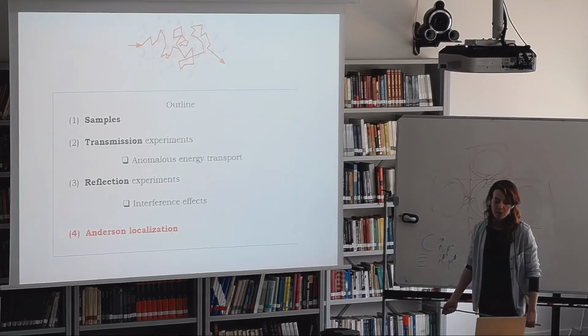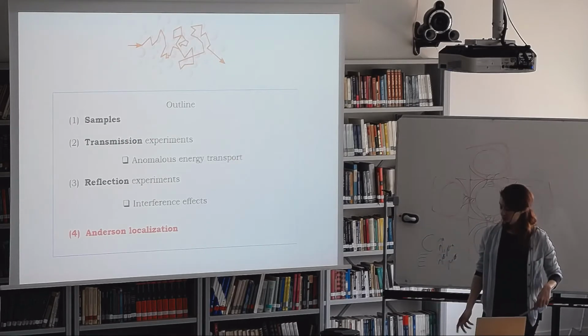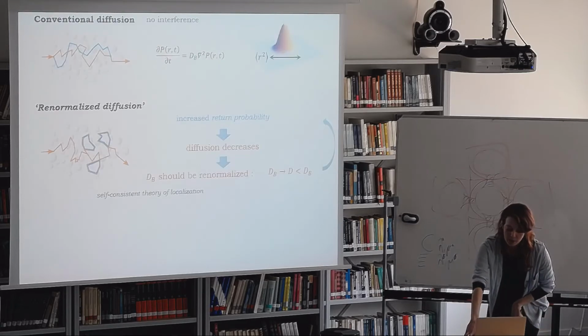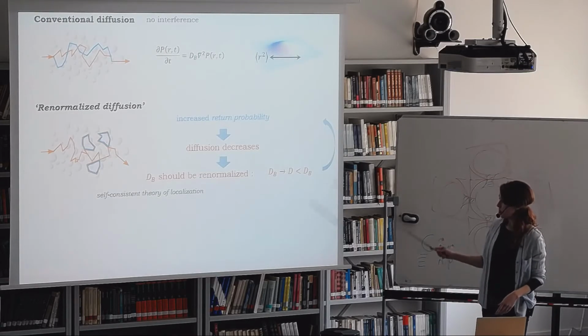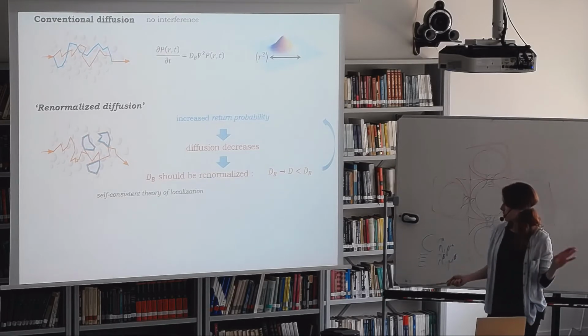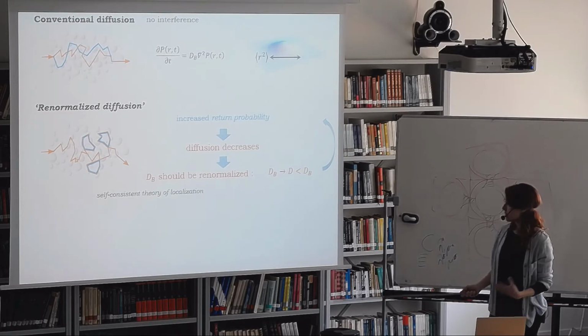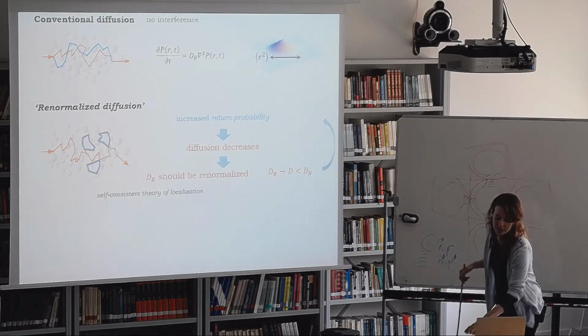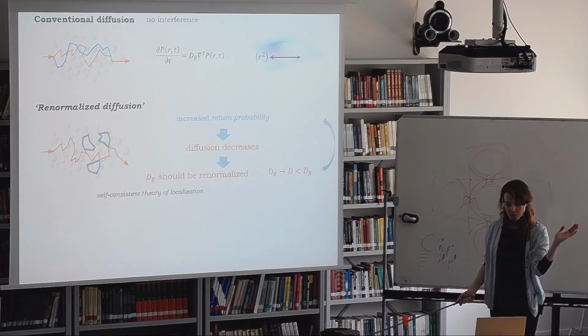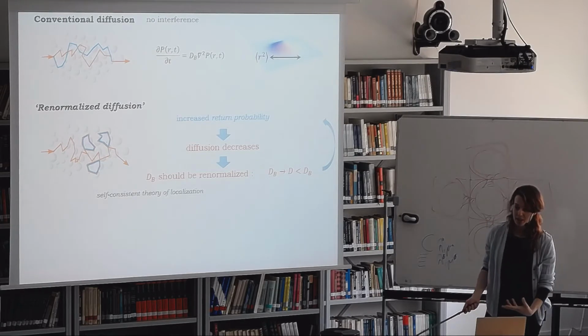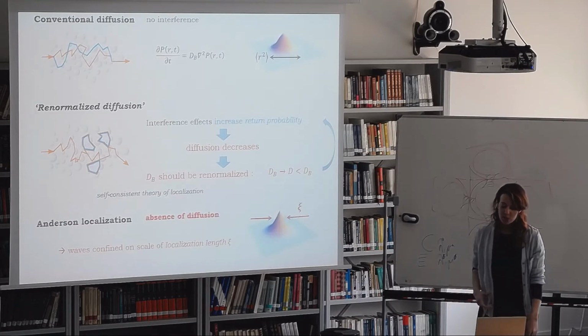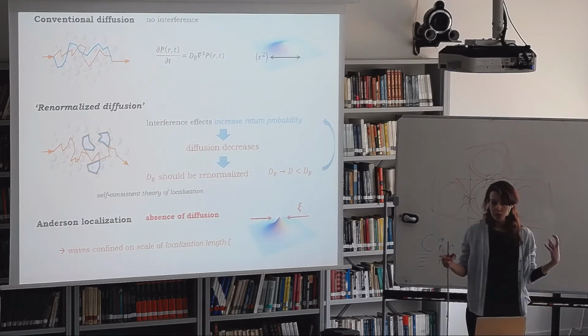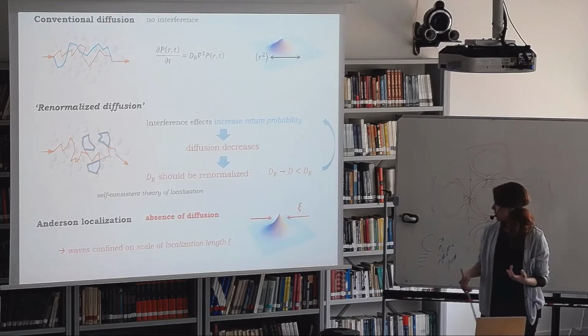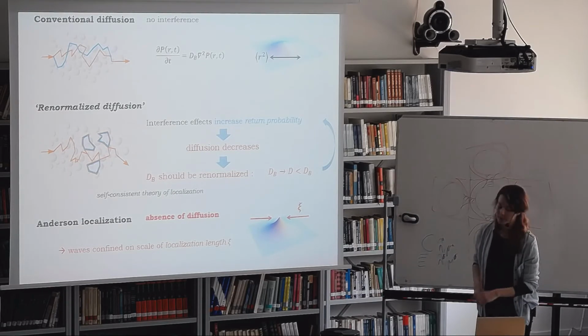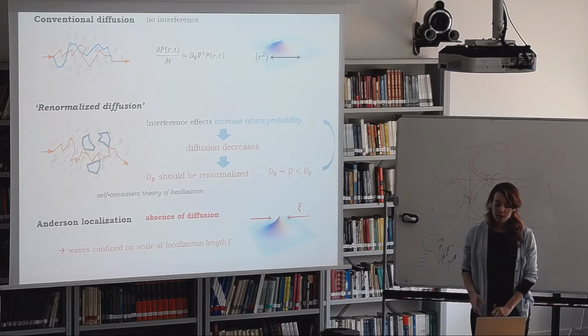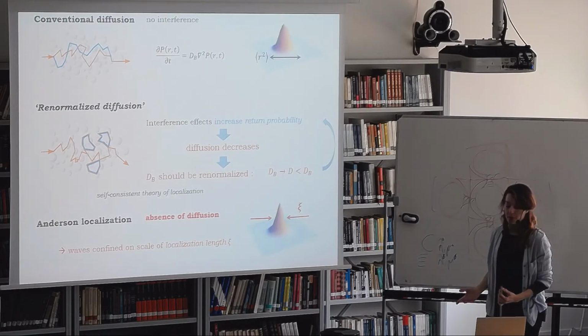So the most extreme end of this is an effect called Anderson localization. I'll go back to this slide. We have diffusion, which is becoming renormalized. So the diffusion coefficient is becoming smaller and smaller. This is actually called the self-consistent theory of localization, because if you follow it to its logical end, the diffusion coefficient becomes smaller and smaller until eventually it should go right to 0. In which case, you don't have diffusion, so the waves become confined in the sample on a scale which is called the localization length. So Anderson localization is really the most extreme example of renormalized diffusion.